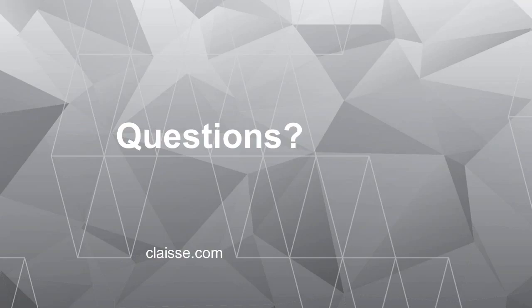Okay, Chantal, let's start with the first question, which is: I recently obtained a cracked disc with chromium oxide samples. How can I solve this? Okay, good question. If all the other factors are the same, which means same flux, same fluxer, same particle size, cooling rate, and you're just having this problem, the first thing to check is the quality of the mold surface, especially because chromium has a high tendency to stick to the platinum ware, so it will be more easily affected by a scratched mold.